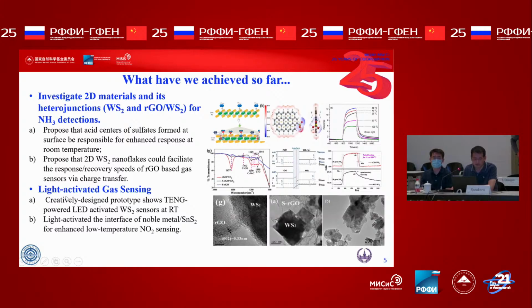We also studied light-activated gas sensing. We creatively designed a prototype showing LED-activated tungsten sulfide sensors which can work at room temperature. We also studied light activation at the interface of the noble metal with tin sulfide for enhanced low temperature nitrogen dioxide sensors.